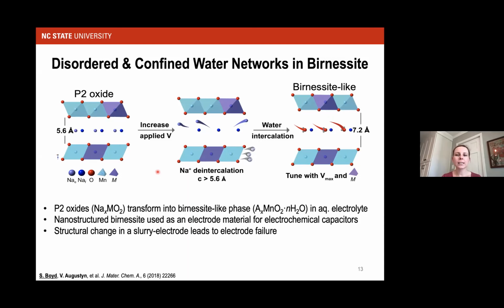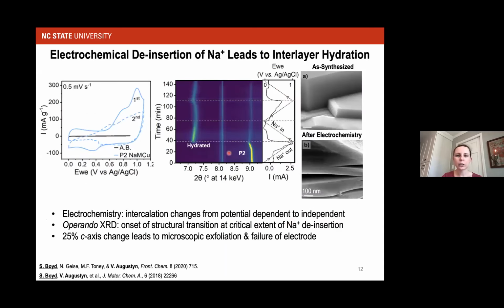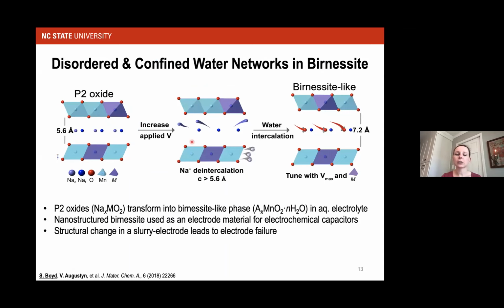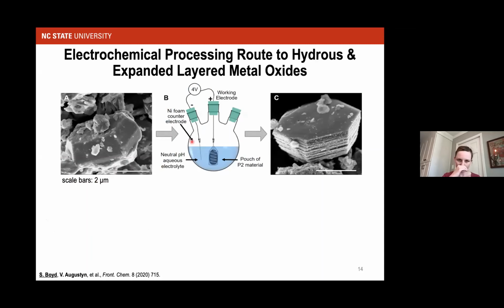But it made us think that if we are forming this birnessite-like material, and birnessite is used as an electrode material for electrochemical capacitors, and the XRD was showing that this phase was electrochemically active, whatever particles were remaining adhered to the electrode were responding electrochemically to sodium insertion, can we harness this process? Can we use this to form bulk-like materials with capacitive behavior?